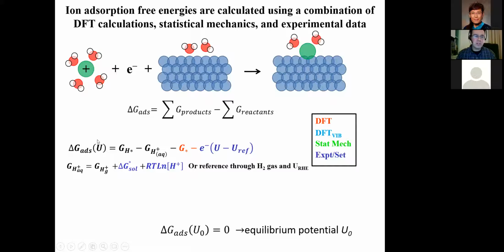The proton in solution is actually not as hard as we think, because we can use some thermodynamic referencing. In other words, we can put in an experimental solvation energy, and doing a quantum chemistry calculation of a proton gas is the easiest quantum chemistry calculation ever, because it doesn't even have any electrons. So we can use some thermodynamic referencing to handle that proton gas. And the voltage is actually not that hard to put in here, because that becomes our independent variable. The energy of the electron just shows up in our equation as the energy of an electron, written as charge times voltage. And there is some referencing there, if you're a practitioner, that takes some getting used to, but we're going to change the energy of the electron and ask how it changes delta G.